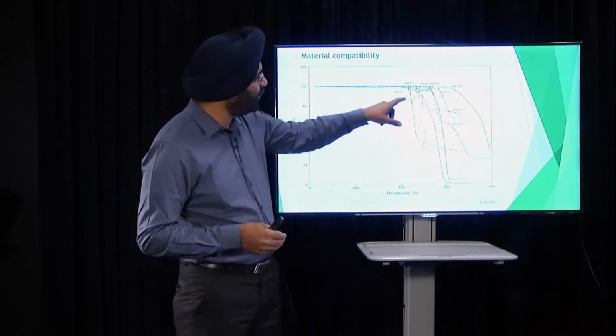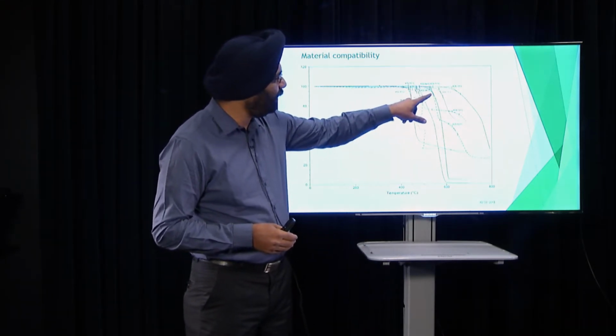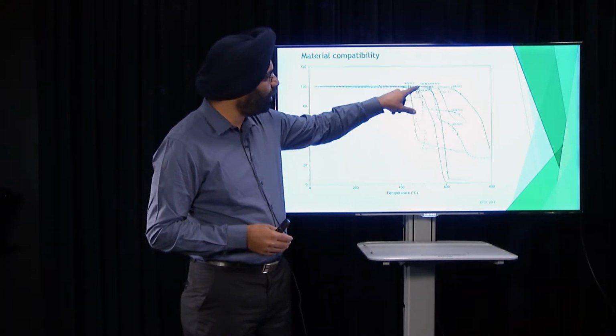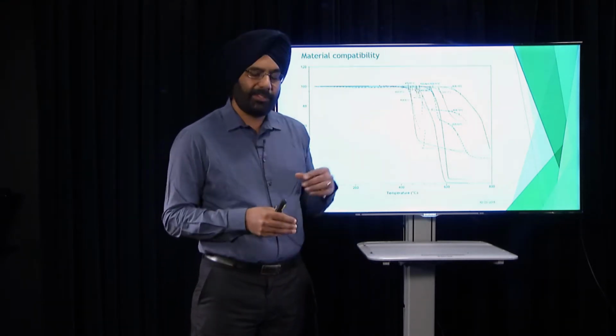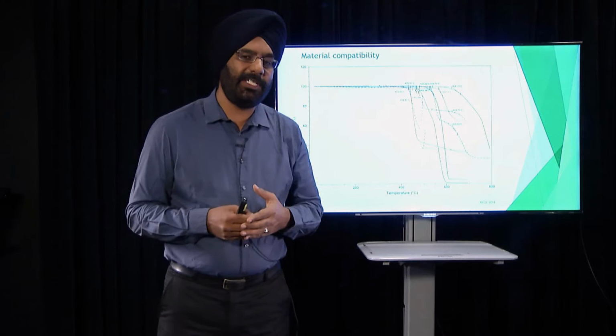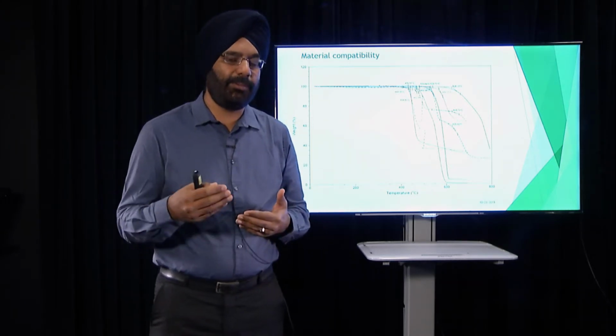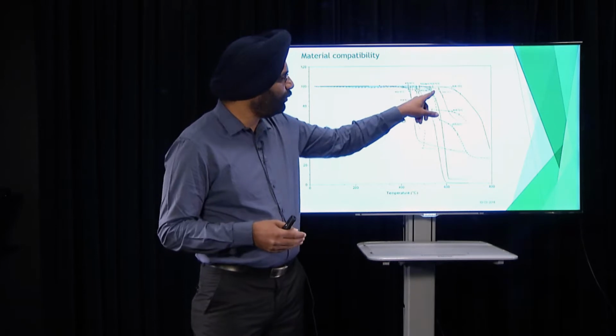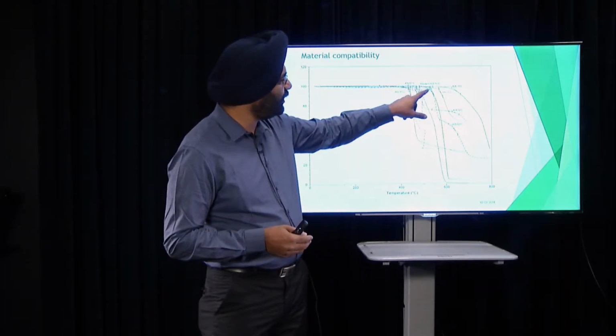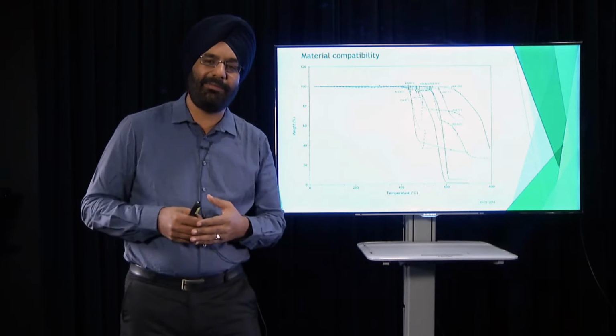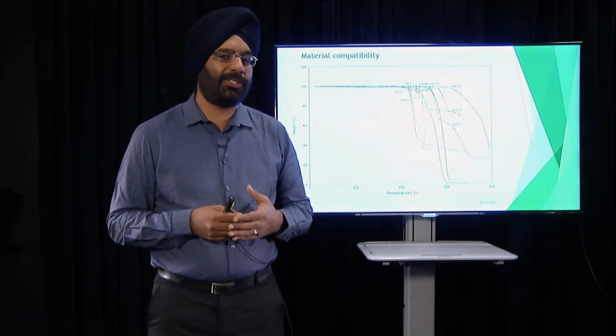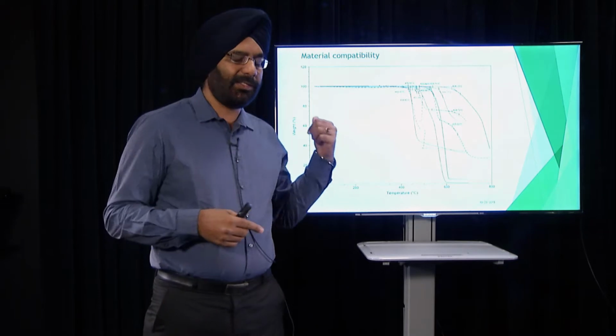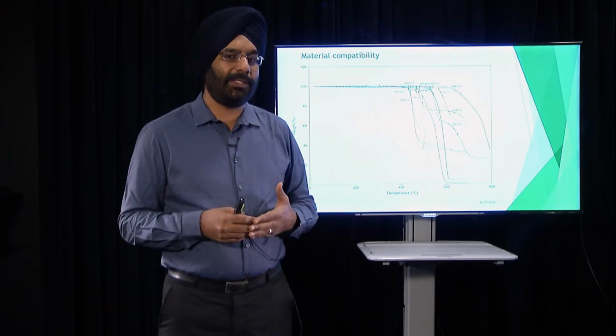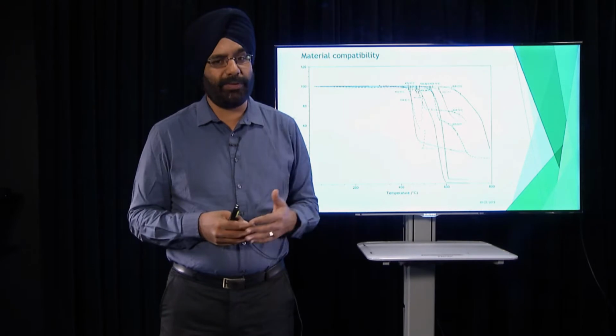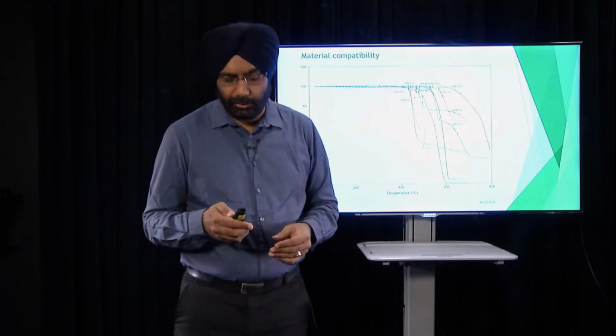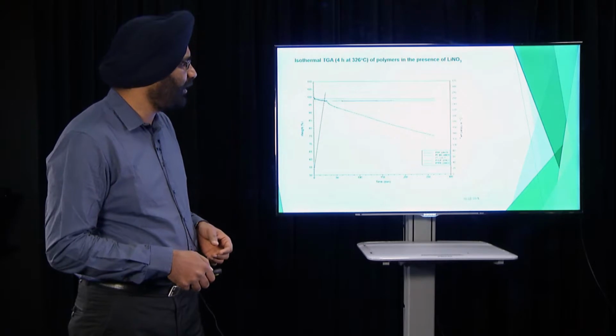But you can see another material here, the green one, with the solid lines and the dotted lines. It's the same polymer, and the TGA was run with and without the molten salt. As you can see, in both cases the decomposition temperature remains the same, around 535 degrees C. The decomposition temperature didn't change, so that means this polymer didn't react with the molten salt. So we said, okay, this is the material which we can use to encapsulate the phase change material.